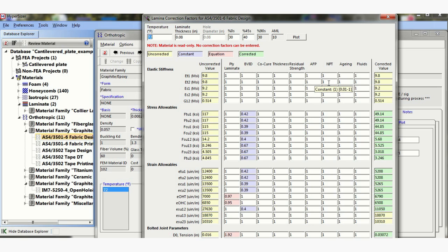NPT, this is where we drill lots of holes for perforation. This is pretty much used in the nacelles. This is where I use this at Goodrich. If I drill lots of holes in the laminate, I get a pretty big correction, and if I drill the holes afterwards and drill through the fibre, I'm going to get a lot bigger correction than you say using the Boeing method where they use the pin, lay up on the pin tool. So this can be a very big correction too.